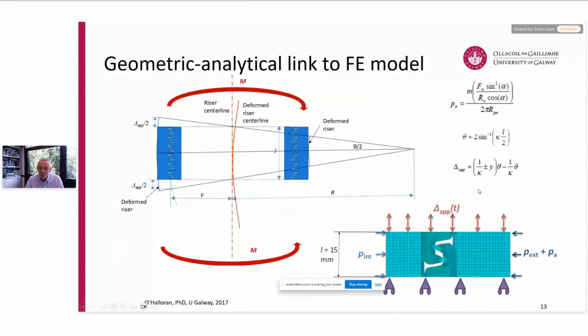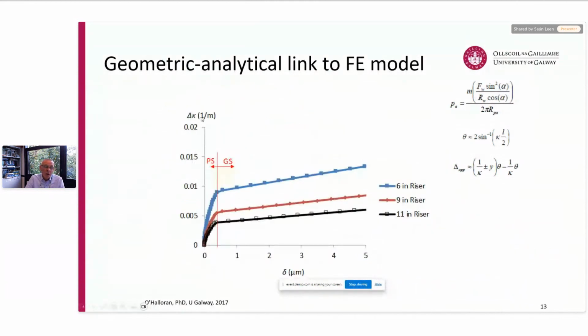We can then use that in the axisymmetric riser model, and also we can estimate the local pressure, the PA, due to the tensile loading on the flexible riser, to also apply that to the axisymmetric model, which you can see in the bottom right. Then we can create these analytical relationships between curvature range, which is coming from the dynamic analysis of the flexible riser, and relative slip that occurs in the nub groove contact region.